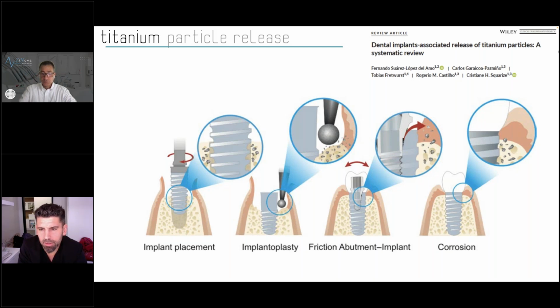This article states that this phenomenon can occur at four stages during implant placement or implant surgery. The first one would be during the time of implant placement. If your implant is placed with a high torque, as the implant is getting screwed in, you could see some of these titanium particles leaving the surface and getting embedded in the bone surface.